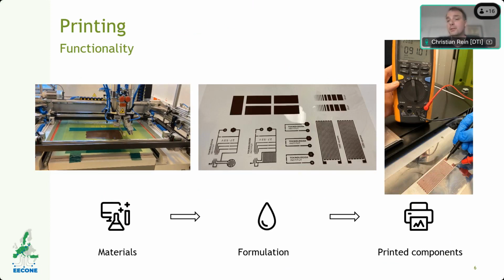After this printing is done, you need to remove the solvent again. Now, just going through the hassle of mixing everything in, you need to take out a lot of the organic material, otherwise you're just blocking the conductivity. And through that, you would first evaporate through the curing, and then you put it through a post-processing step of sintering. For example, with copper inks, you need to make sure that the copper particles are being fused together through this sintering process in order to provide the macro scale conductivity throughout the entire length of the electronics.